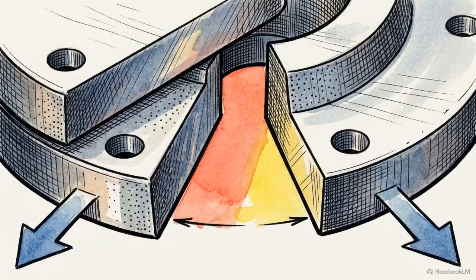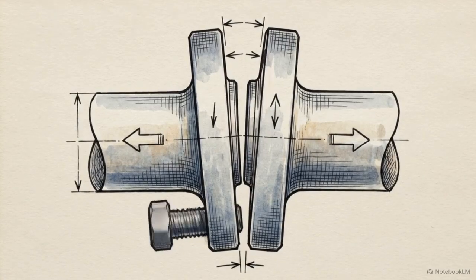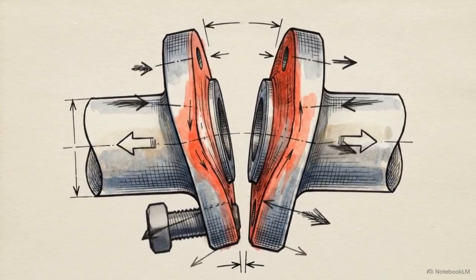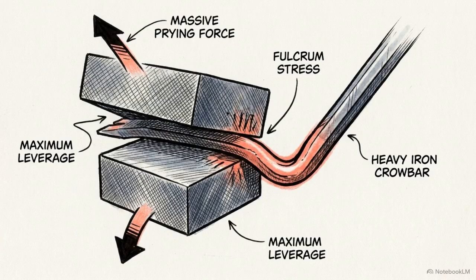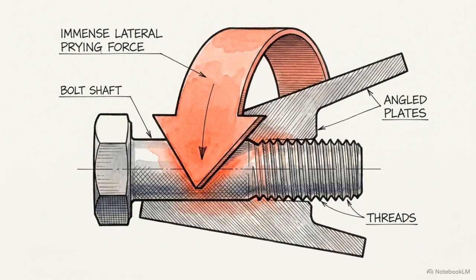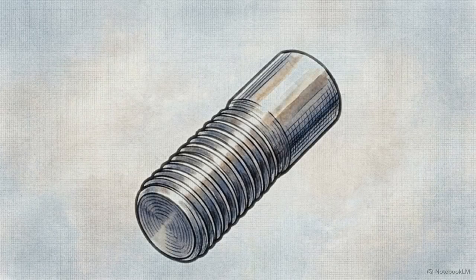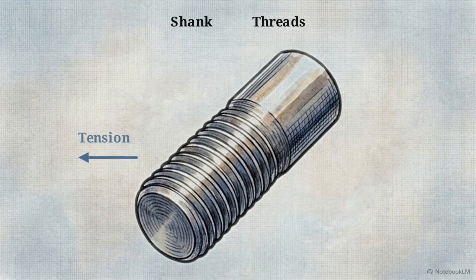The massive flange faces were left hanging at an angle, creating a wedge-shaped gap down toward the bottom 8 positions. Tightening the bottom row of bolts forced the thick steel flanges to bend closed against their own rigid geometry. This negligent, non-parallel assembly turned the rigid steel of the flange into a massive crowbar, leveraging immense prying force directly against the lower fasteners. This cross-section illustrates the severe bending forces generated by that assembly error, intersecting directly with the system's geometric flaw. While the fastener attempts to hold linear tension, a massive perpendicular bending vector pushes hard from the side, combining perfectly at the thread runout.